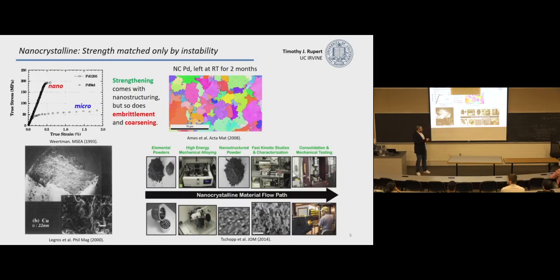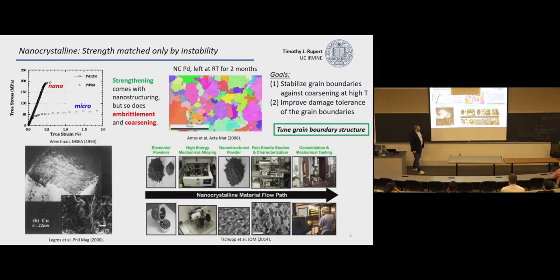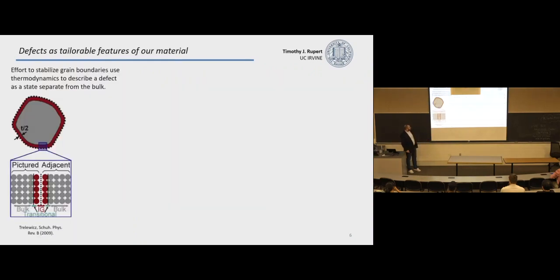And often that requires things like using high temperatures and high pressures to consolidate these things into bigger pieces. So your material needs to be able to survive that extreme environment as well. So the goals here, if we want to address these two issues, are that we need to think about improving the damage tolerance of the grain boundaries, so we can get rid of that brittleness problem, but also stabilizing those grain boundaries against high temperature. And the pathway we've been going down is that if both of these properties come from the grain boundaries, let's think about changing the grain boundary structure, so the structure of those interfaces between those crystals.